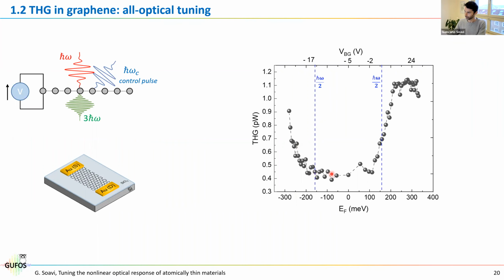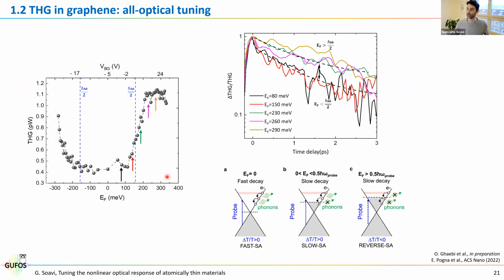Then the second thing that we do is we select some values of the gate voltage, and we perform all-optical modulation. So we fix the gate voltage, we arrive with the control pulse, and we look at how the third harmonic evolves. Here I'm plotting again how the third harmonic is changing as a function of time for different values of the Fermi level. Now, this is normalized. All these curves are negative. So we have a reduction of the third harmonic, but I normalize them because I want to show you a comparison between the dynamics.